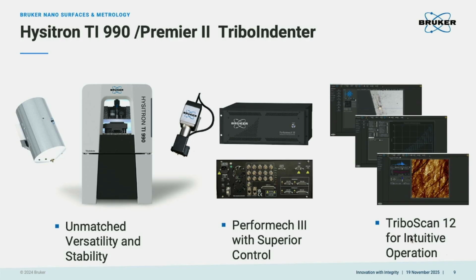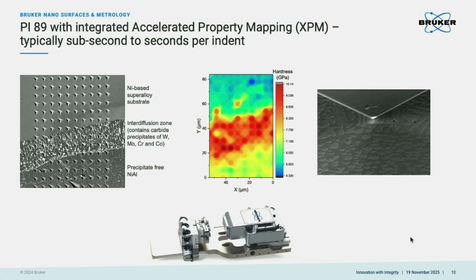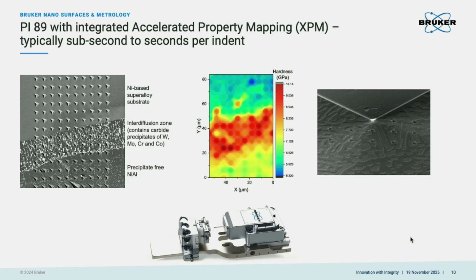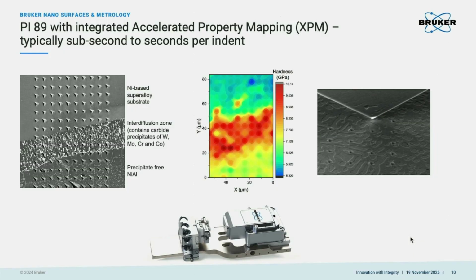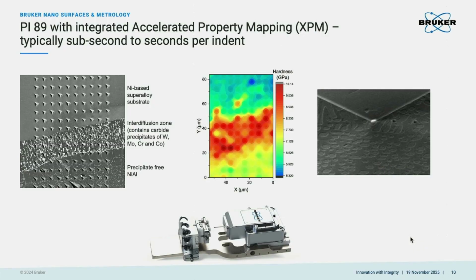Yeah, of course, we have the new software and controller, and also the low-noise transducer that allows us to do high-speed mapping. We can also perform high-speed mapping in the SEM as well, right? This is a video of the high-speed mapping at real speed. We don't speed this up. This is just a real image, almost 1 second per indent, inside the SEM. You can see very clear images of different interfaces and different phases of the material, and you can see the mechanical properties after the high-speed mapping.